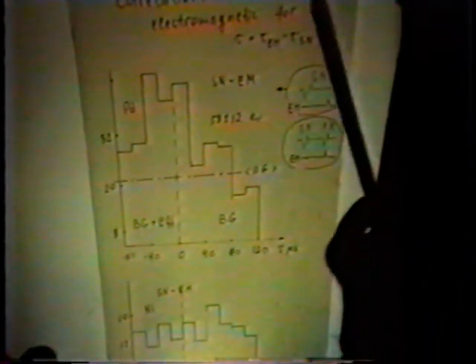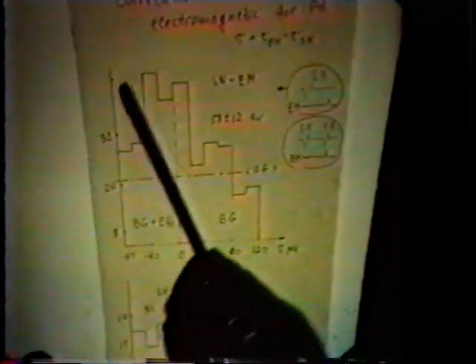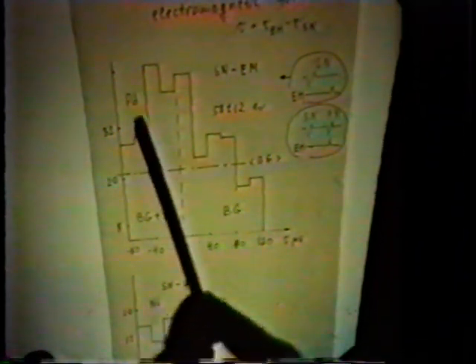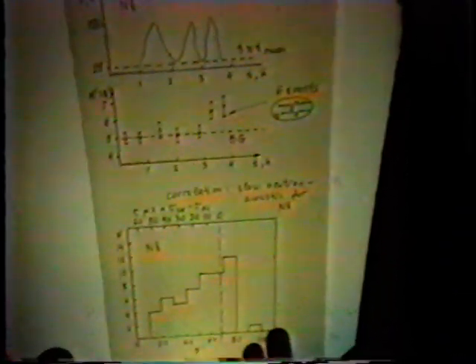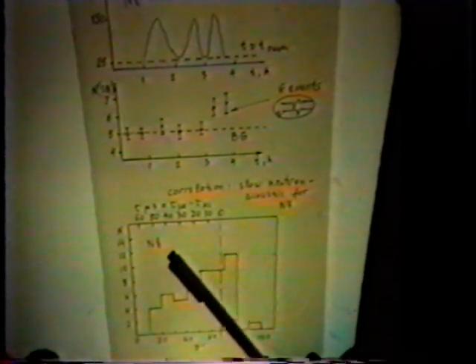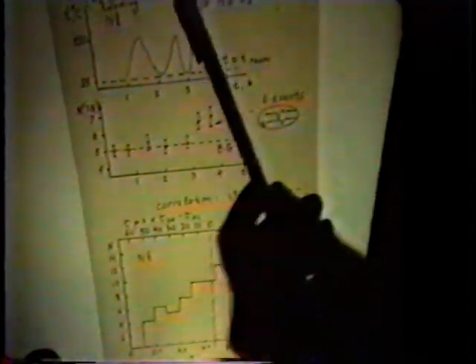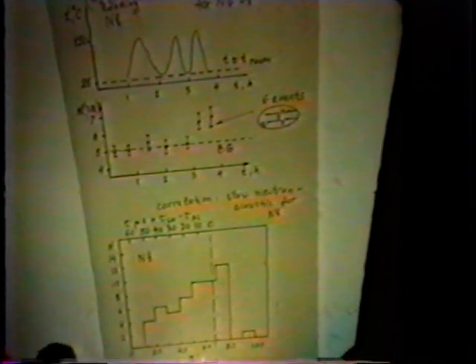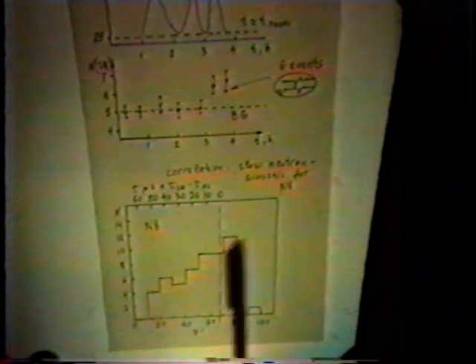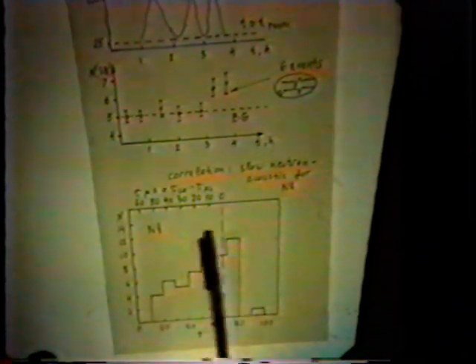This picture illustrates the results of measurement of correlation between slow neutron and electromagnetic signal. Again, red is results taken from a palladium cathode and blue from a nickel cathode, and you can see the difference. There are some correlations for the palladium cathode. This picture presents results taken with another kind of material, niobium. In this case, they used another procedure of loading from the gas phase, and they used thermodesorption with pulsing temperature during the thermodesorption run. And they observed again a number of correlation events.